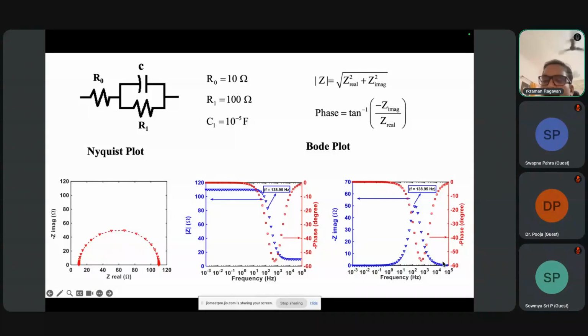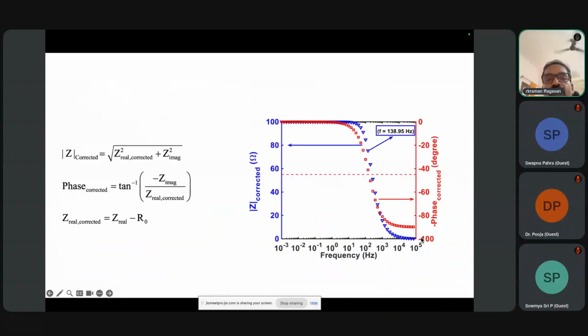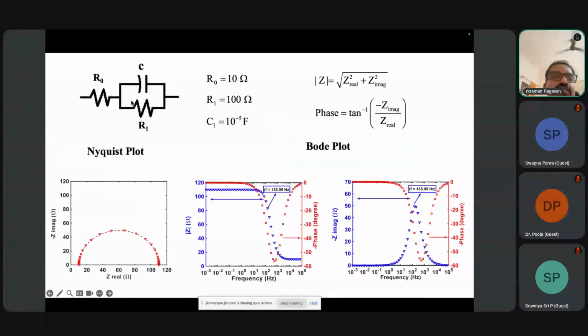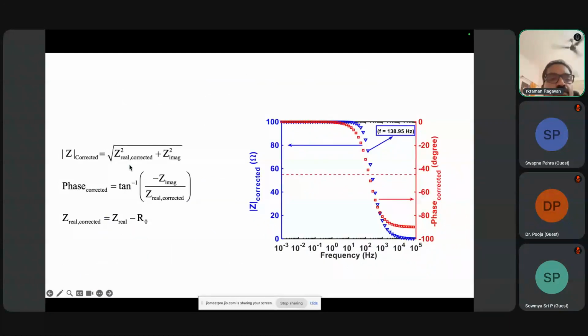Okay, this can also be plotted like this using imaginary resistance, showing how it changes. Again, imaginary resistance comes only when you have a capacitance. At low and high frequency, you don't have capacitance effects, because it either doesn't exhibit any impedance or it exhibits a very high impedance. Therefore, the capacitor's role is minimal in these two regions. So only in the mid frequency region you see the capacitance, right? So now we can also have a corrected impedance, because in this case we have an R0 here. If you correct for that R0, subtracting it from the real value, it's called the total impedance corrected for the solution resistance. You can use that to estimate exactly what the characteristic frequency is in the system.